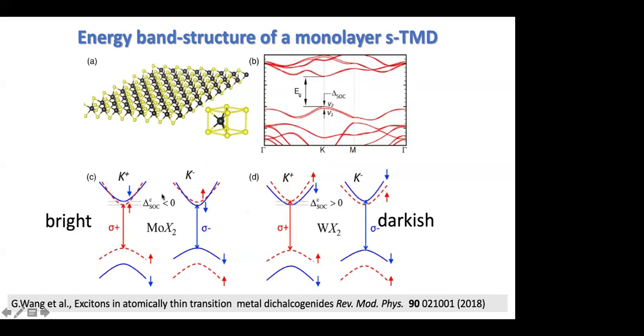And what are those results? The spin orbit interaction splits both valence band and conduction band. This splitting appears as a difference between A and B excitons I have shown just before. But the splitting also takes place in the conduction band. Okay, so both valence band and conduction band are split. The crucial point is the order of those minima. Apparently, depending on if we are dealing with molybdenum or tungsten material, there is a difference in this order.